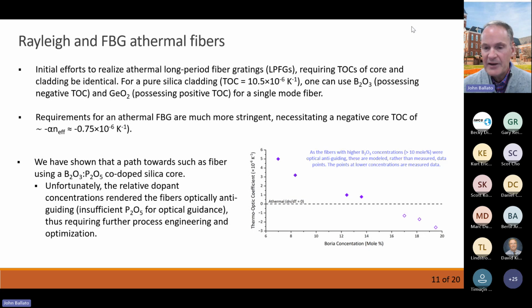But we have made fibers that, at least compositionally, would be in excess of where you have a zero thermo-optic effect, and that would give you an athermal fiber Bragg grating structure or sensor structure, long period grating structure. If you also have to take into account things like the thermal expansion, which is the alpha in the equations above, then you need a slightly lower effective thermo-optic coefficient, which means you'll need more of the dopants. But that becomes very interesting for athermal gyros. So those folks that are interested in gyroscopes that are not temperature dependent, then this is a route to doing that. All right, moving along.